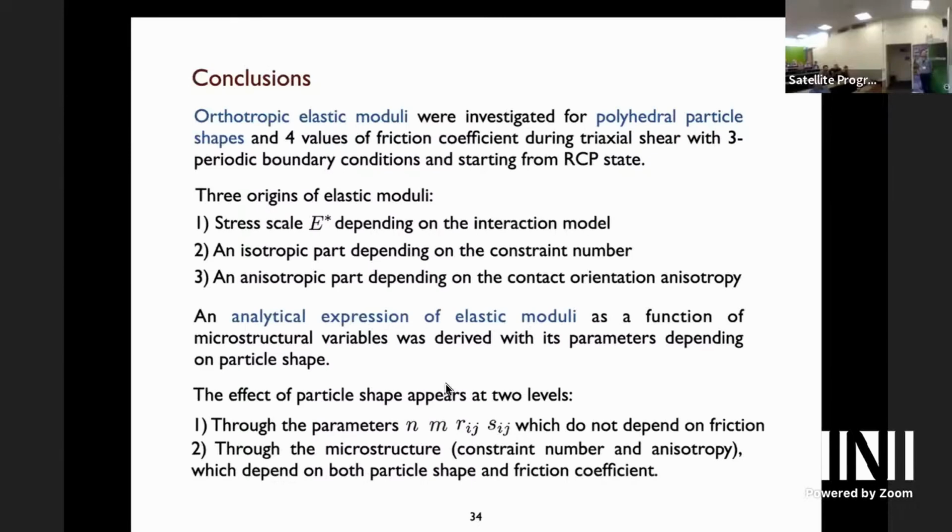But I guess I'm struggling with this notion. For example, I know when you have face-edge contact, there's no way that can be Hookean, right? Because as you press the edge into the face, the contact area is changing. Yes. And even if I have face-face contact, depending on how much face and how much face touch each other, I should get a different stiffness, right? But in your model, did you say that every one of these contacts has the same Kn? Yes, that's the right question.